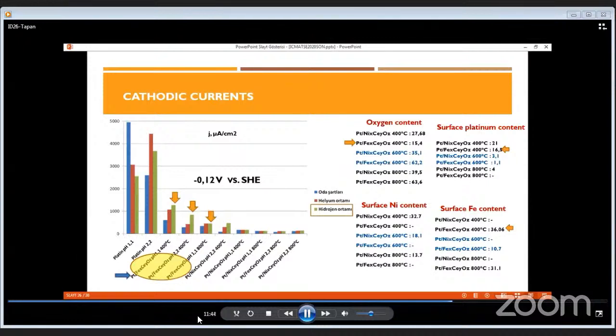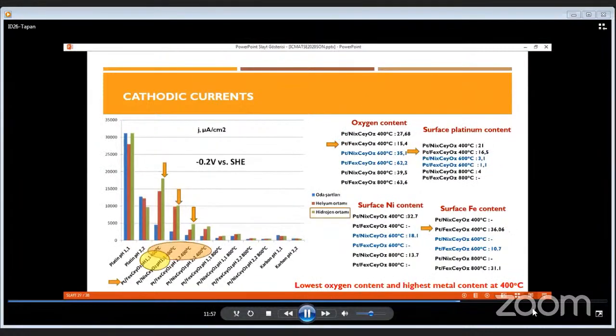As we have mentioned before, regarding the dominant parameter catalyst type, platinum iron cerium has high platinum and iron content at the lowest oxygen level. Looking at cathodic currents at low potentials, at -0.2 volts, we see that again the most dominant parameter is hydrogen purging, and in addition reduction temperature.